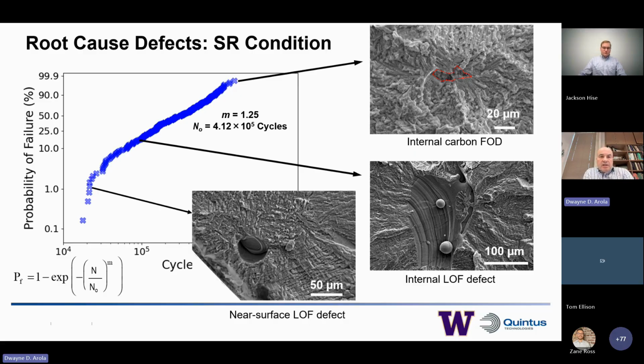All right, many times, looking at fatigue responses, we like to examine the statistical distribution in the data. And so here I'm plotting Weibull distributions for fatigue life responses, the vertical orientation from 3 partners that I had represented earlier. This is for the stress relief condition here, indicating a Weibull modulus and then the shape parameter. And this is a 2-parameter Weibull distribution. So what I'm going to point out here now is the value of doing this is that we could pick out the kinds of defects which contributed to our low life samples, our medium life responses.